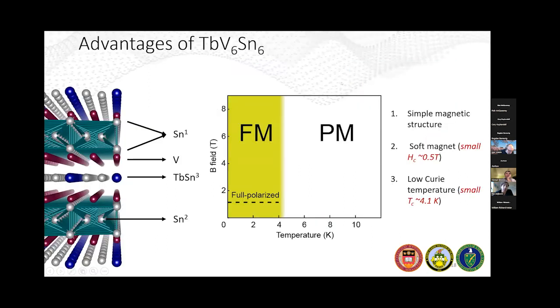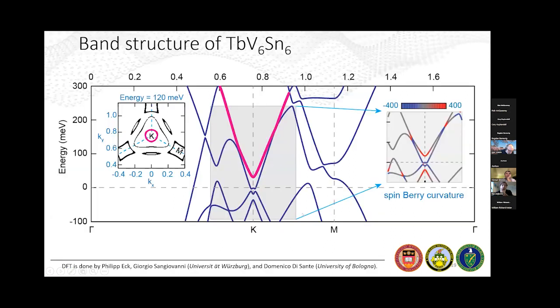The reason why we chose terbium vanadium tin is that it's a nice soft ferromagnet, with a Curie temperature of about 4.1 Kelvin. Unlike yttrium manganese tin, which we started at the beginning of the pandemic, this is one of the systems that we just had lying around, and it turned out to be very interesting. This was very targeted because both the Curie temperature and the coercive fields are well within the range of STM.